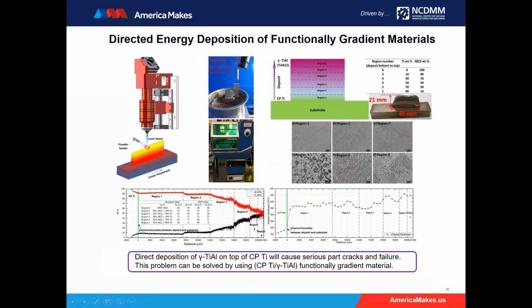So in this case, we change the material composition from pure titanium to gamma titanium aluminide. And you can see we have regions from 1 to 6, changing the composition between the two materials from about 100% of one material to 100% of the other, going through a gradient change of the composition. You can see that the microstructures are different, the compositions in terms of titanium content and aluminum content are different, and the hardness is also different. And this is very important. This allows us to have a lot of flexibility to build parts with not just a single material.